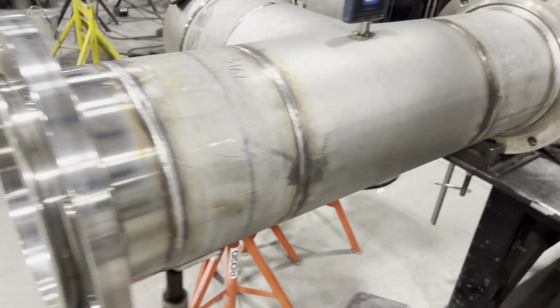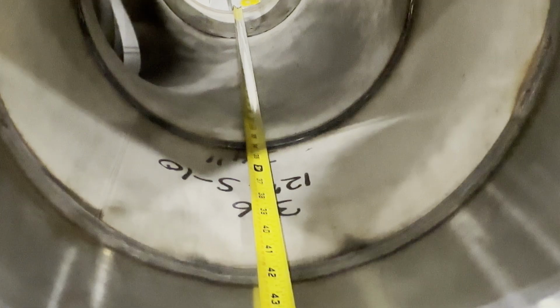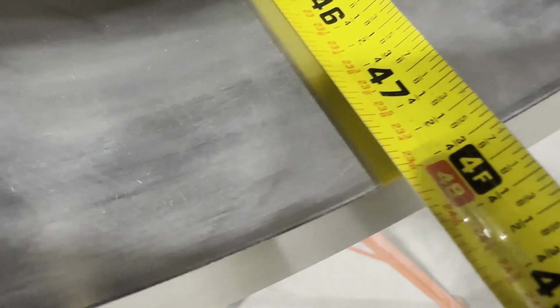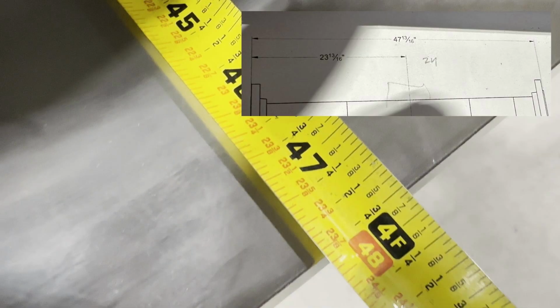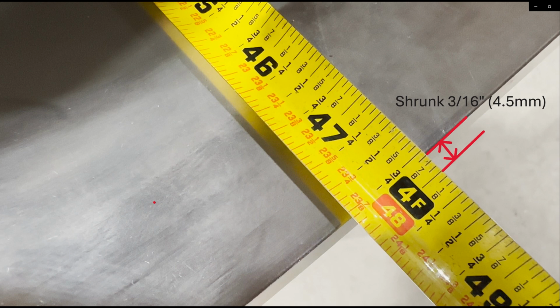Let's measure the length after welding. It is 47 13/16, bang on as requested on the drawing. It was 48 inches before welding, but it shrunk about 3/16 after welding. You can see that it shrunk about 1/16 per weld joint.